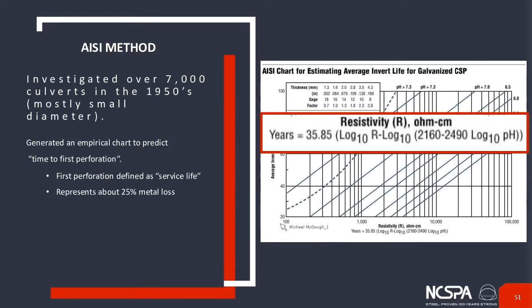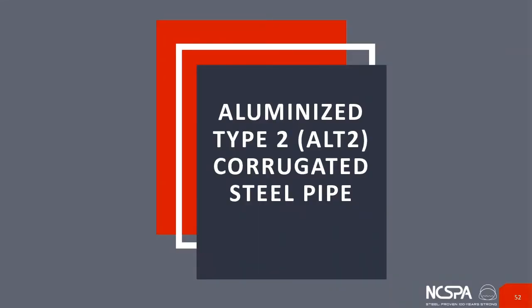So again, what AISI did is they looked at first perforation at 25% metal loss. So that's a longer time duration to get to your first perforation. And then what that results in is a slightly different equation where this multiplier moves from the 17 that you saw to 35. So that can have a significant impact depending on the environmental ranges.